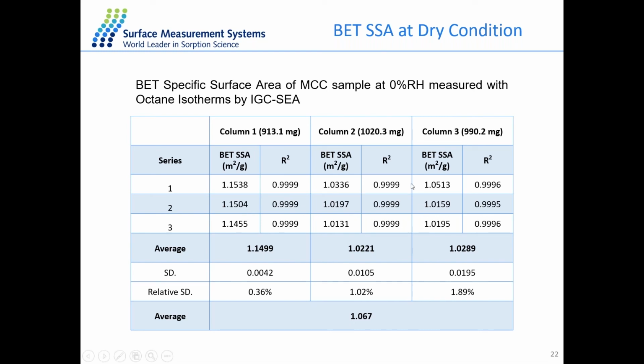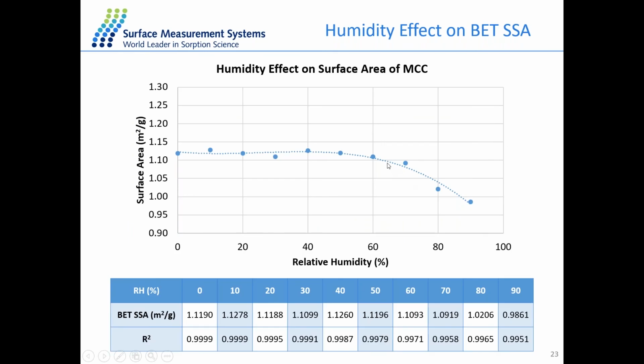And one of the advantages of the IGC technique is we have a background humidity controller inside the system that allows us to investigate the humidity effect on these surface properties. So we can perform very similar octane sorption experiments at a series of different humidity conditions. So here we performed from 0 to 90% RH. And as you can see, the surface area of this microcrystalline cellulose sample is quite constant and stable below 50%. So the surface area is just about 1.1 square meter per gram.